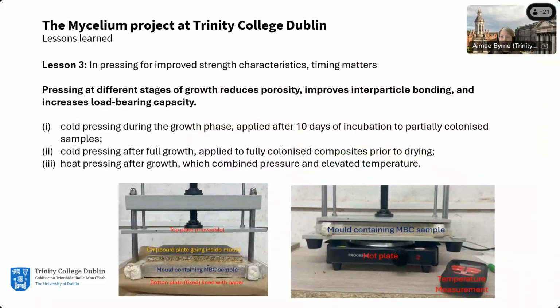Our third lesson is that when we are pressing samples, when we press them really matters. We tried pressing them in the interim, so kind of halfway through their colonization. We tried pressing them at the end of colonization when it looked fully white, and we also tried hot pressing them, and there's quite a marked difference between the three.